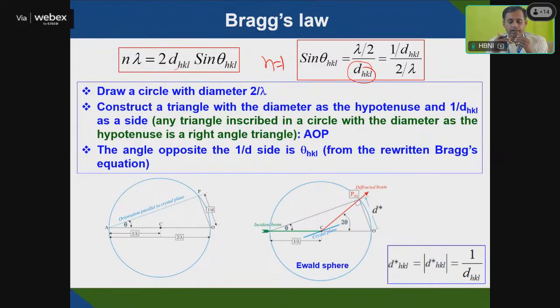When you go for X-ray diffraction analysis, you get a diffraction pattern, but that pattern is generated from the diffraction spots obtained in a reciprocal lattice. From the reciprocal lattice you convert to the real lattice, and all of this is now taken care of by the software, and you get a diffraction peak. If you want to see how it happens, first draw a circle with diameter 2 by lambda. So this is my circle, which has 1 by lambda as its radius.